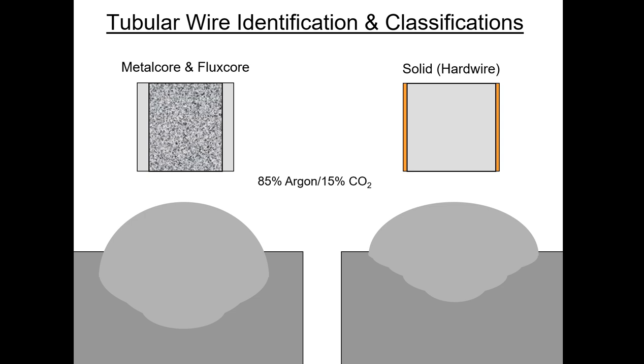So just a quick pictorial to understand that the metal cores and flux cores had more penetration. The answer would be because these areas only on the outside, this is a tube, and the areas on the outside were the only areas that actually got electrified. So the arc density, the amount of power, is all on the outside, right where you want it, and confined to that area, so you always get more penetration on your outside edges. With the solid wire, you get a decent penetration profile, usually everything we need for the automotive applications that we're playing around with.